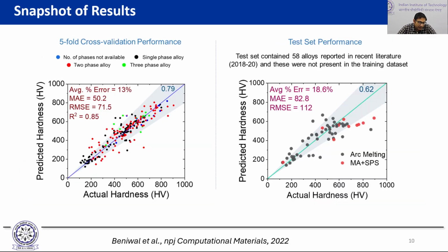After you develop the neural network model, you want to cross-validate it heavily. So 5-fold cross-validation was done, and most of the time you can see that the predictions fall within a 20% error. The overall R-square value in this case came out as 0.85. When you do the cross-validation, you have to look at the R-square value in each fold, and you need to ensure that those values are not changing quite significantly. Once that is done, you know that you have a reasonably good cross-validated model.